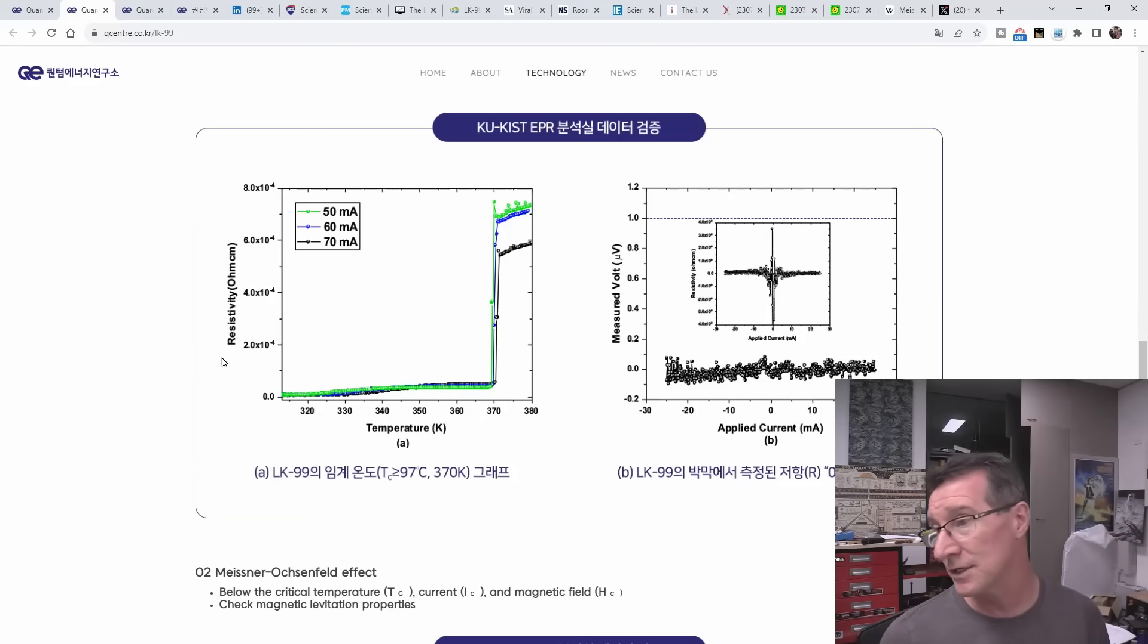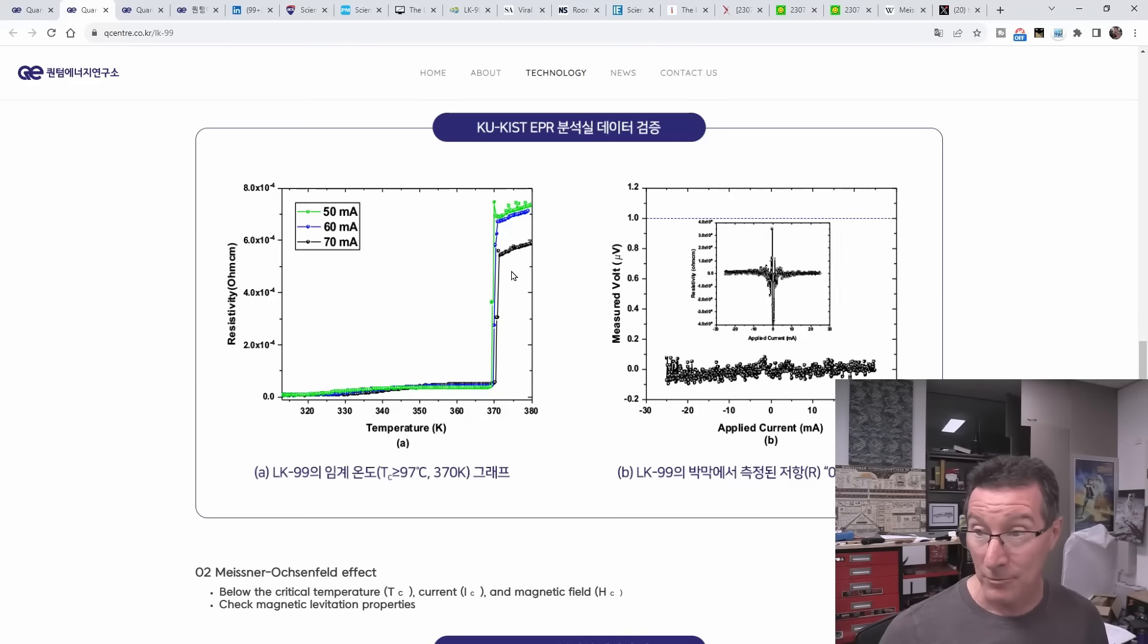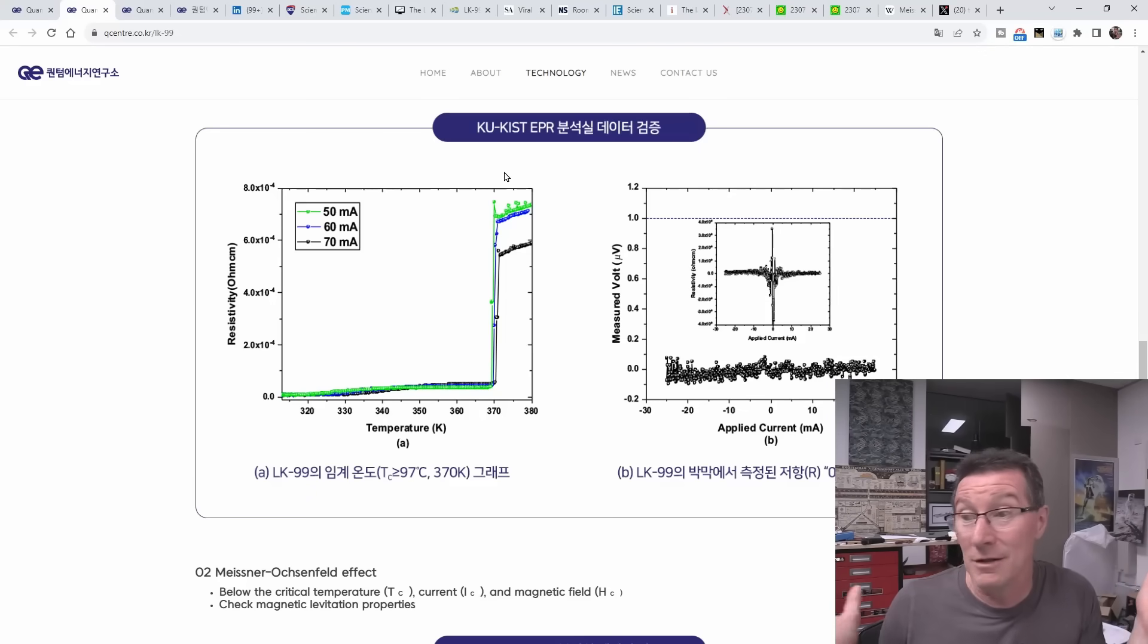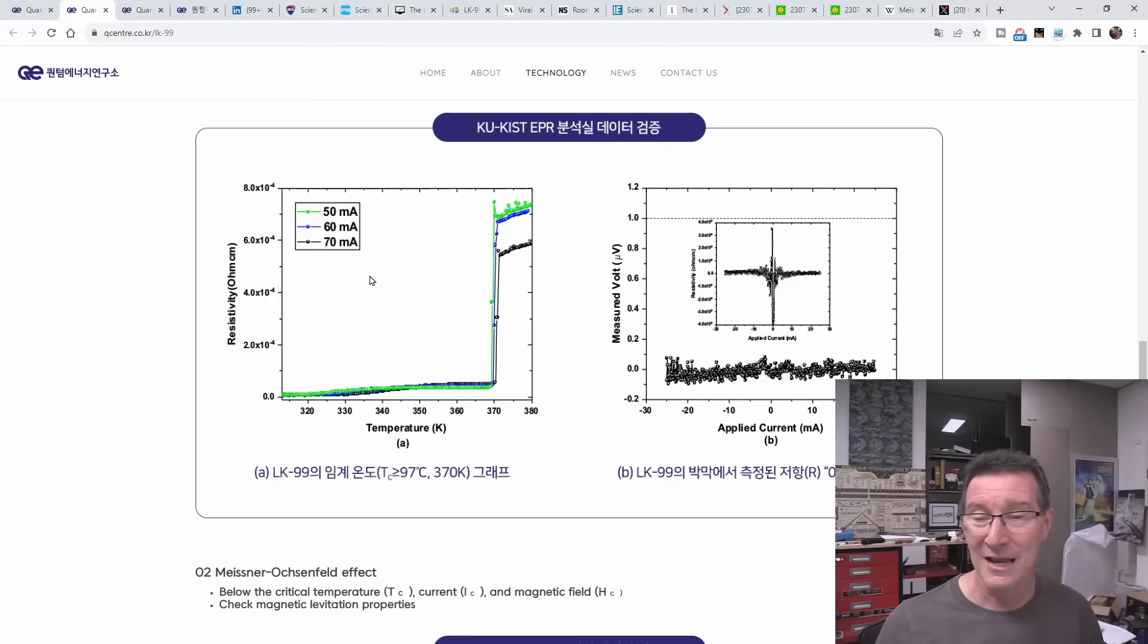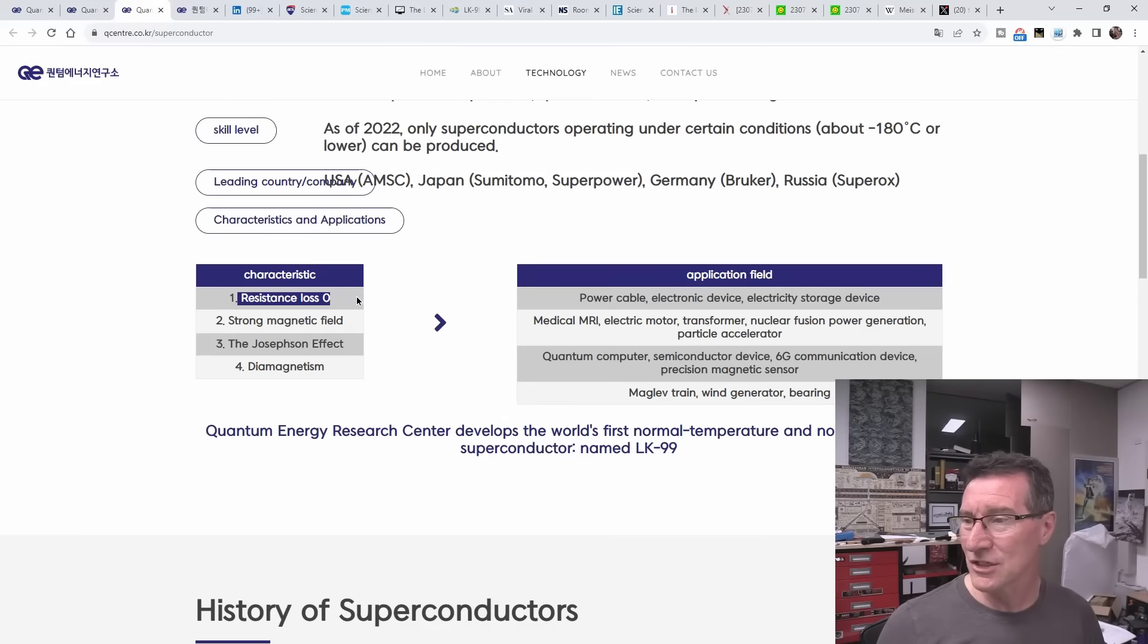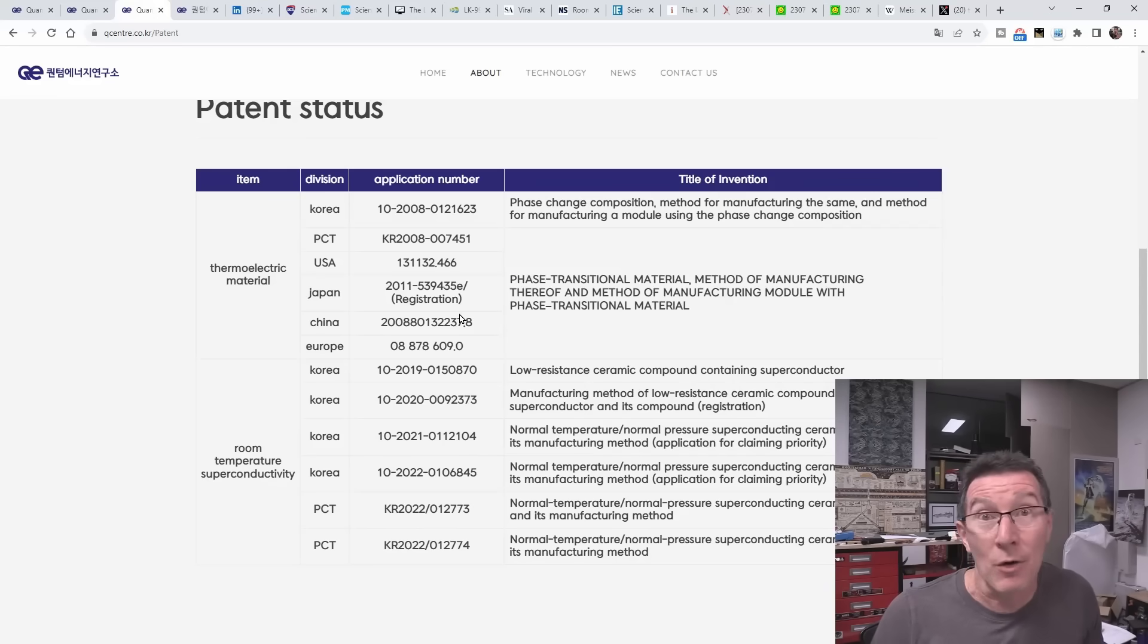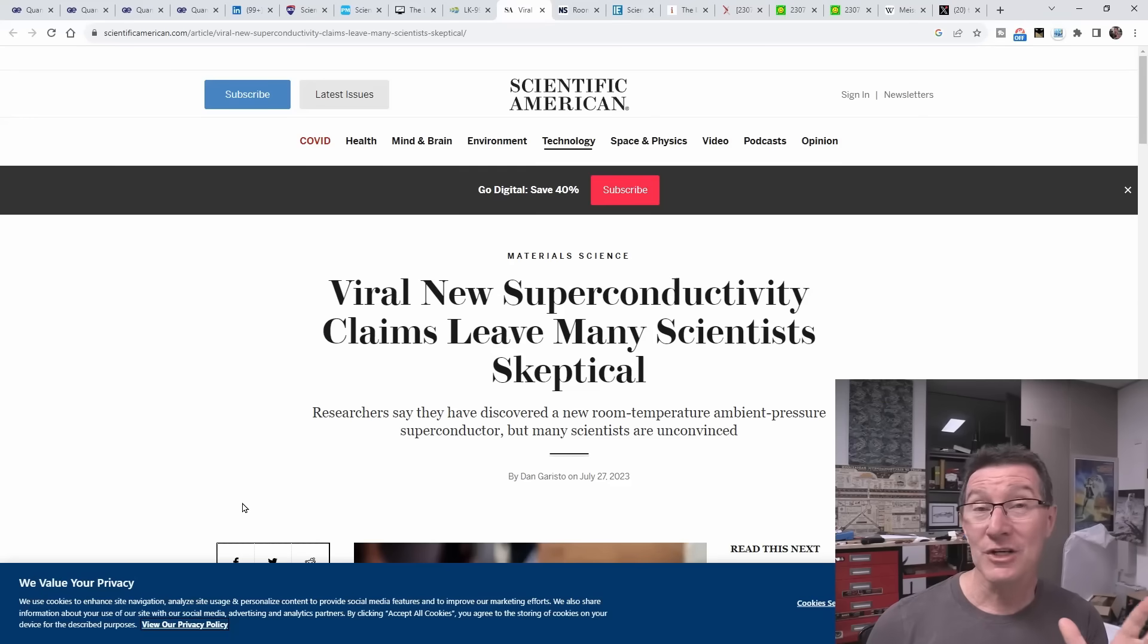Then it jumps up at 370 Kelvin - it's no longer a superconductor basically. 370 Kelvin is like 96 degrees, so from right up to 100 degrees Celsius it is a superconductor. The test currents are only like 50, 70 milliamps, so it's not big energy stuff yet, but this would genuinely be a big deal if it's true. They do claim a resistance loss of zero, so I'm not sure what the deal is. Here's their various patents that they got. This is a commercial - they want to commercialize this. This is what the research center's set up to commercialize superconductor technology.